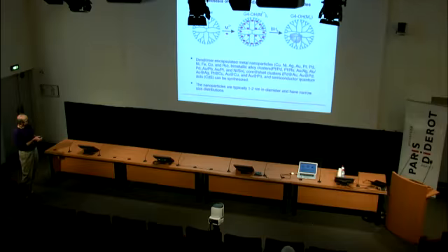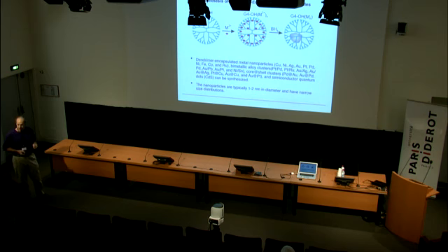So if it's an ideal dendrimer, 62 of these metal ions will partition into the interior and be very strongly bound to the tertiary amine sites. Now if I add a reducing agent like borohydride, those 62 ions will be converted into 62 atoms. That's an energetically very unstable situation. Those atoms would like to nucleate and grow, and they do very quickly, faster than we can measure, into a single particle. And that particle now is trapped inside the dendrimer, but primarily sterically.